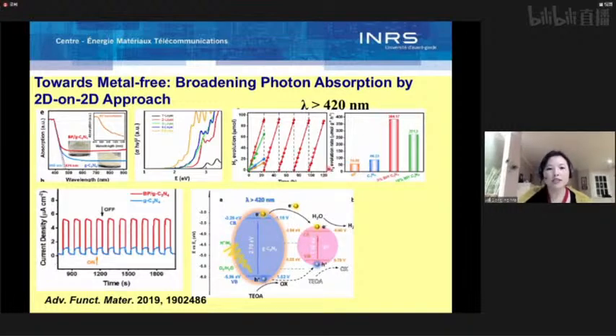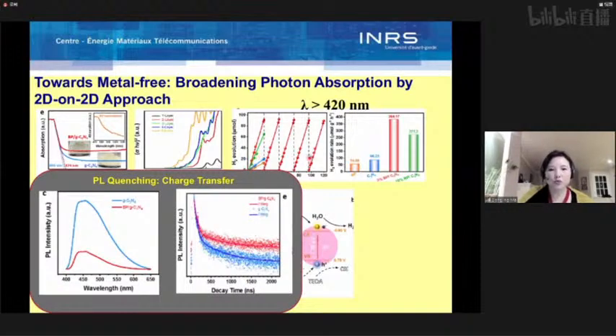And this increase can be easily explained by this energy level diagram. So we measured energy levels, and you can see C3N4 and BP basically form a type 1 junction. C3N4 mainly absorbs photons to generate electron-hole pairs. Electrons can be injected into BP used for photocatalysis, and holes can be directly captured by scavengers. So in this case, hydrogen generation is largely enhanced. And the charge transfer from C3N4 to BP was also confirmed by the decrease of photoluminescence intensity and the shortening of photoluminescence lifetime of C3N4. So we confirmed that by combining C3N4 with BP, we show largely enhanced visible activity.